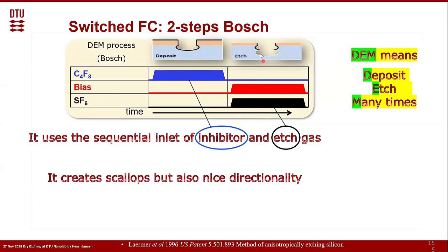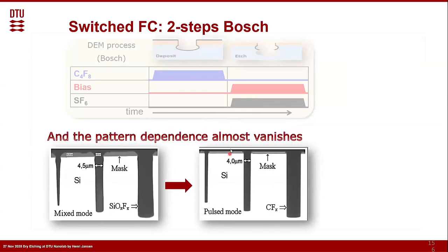So by doing this in a cycle, it creates scallops, what we call these things over here. So 1, 2, if you go every step, you get these, and this will continue. They're called scallops, but it's also going to be nicely directional. For instance, if you compare the mixed mode to this switch mode, you can see that the passivation at the top is gone. It's much less pronounced, and also the profile dependency is much better in this one.